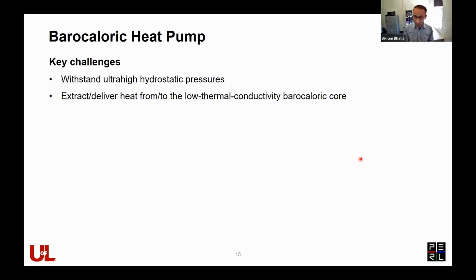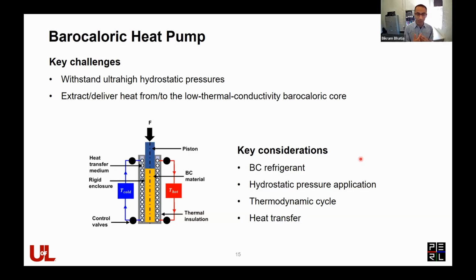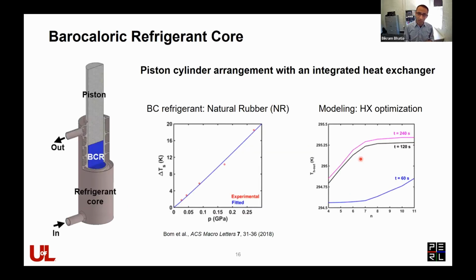So that is somewhat challenging. So those are the two key challenges we focused on, and we went again with a simple piston cylinder kind of idea with an elastomer as our barocaloric material, which we chose as natural rubber (NR), which has a Poisson's ratio of around 0.5. So when we apply this hydrostatic pressure on the piston, the pressure gets equilibrated within the solid media fairly uniformly. And so we focused on the core first.